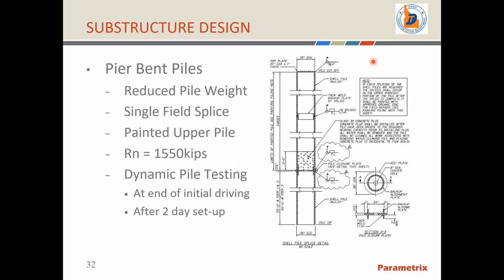The piles were driven to achieve a nominal capacity of 1,550 kips. That was achieved by first, like I said, driving open-ended the first 55 or 60 feet till the closure plate came in contact with the stream bed down below. You were able to observe that right away in the field because the hammer height would dramatically change as they're driving the pile. And then they were forced to drive the pile an additional 3 feet after the closure plate came in contact with the stream bed.